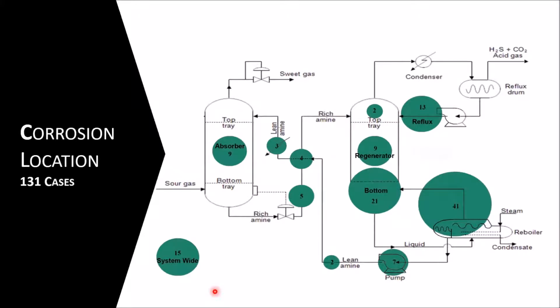Now, one thing you will note is that if you're operating a plant or you're an engineer in charge of that plant, corrosion is generally highly localized. You never go to a plant at a turnaround and see corrosion in every piece of equipment. Corrosion is very highly localized. So this number made sense to us. And a number that might not make sense to many of you is if you understand that H2S and CO2 are corrosive, and you look at an amine flow sheet and you say, okay, where's the most acid gas? It's right here, and it's right here in the rich amine solution, and obviously up here in the acid gas.